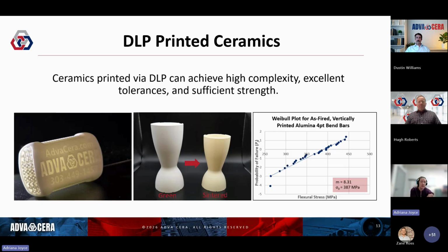Despite this, we can produce parts that meet the specifications required by demanding aerospace and semiconductor industries. For example, if we print B-size bending bars, so 3 by 4 by 45 millimeters, vertically, and don't post-process them at all, so the surface texture that comes off the printer and out of the furnace, we can get a Weibull modulus of 8.3 and a characteristic strength of 387 megapascals. This is the worst case scenario for strength testing because any of the surface defects are still there and the force is being applied parallel to the layers. So it tests the interface strength as much as the inherent ceramic strength.